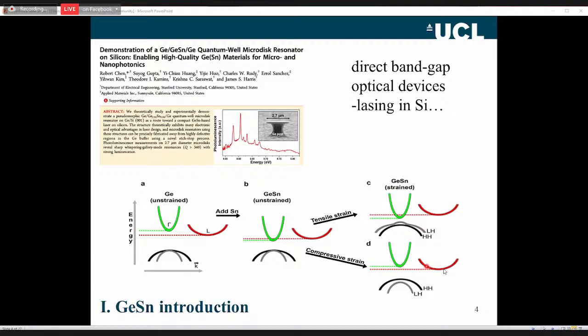The L minimum drops down again. If we were to somehow have a tensile strain, perhaps grown on silicon, the silicon has a smaller lattice constant. Right on silicon, the crystal would have to be under tension rather than compression. Then the direct band gap reappears again. So that's why germanium-tin is interesting, that it opens up this possibility of direct band gaps in silicon-based structures.